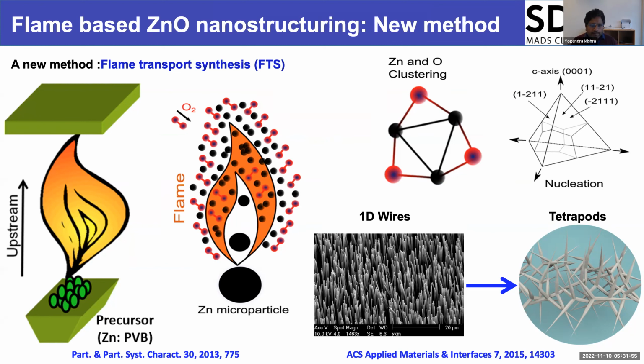nanomaterials, whatever. So in the same approach, I developed a recipe where we take zinc microparticles and polyvinyl butyral as precursor materials. We fill them into a ceramic crucible, and then we put it at high temperature into the oven. Due to the high temperature in the oven, this polymer burns. It generates a flame which carries these particles away into the flame. And due to the high flame temperature, these particles are converted into atomic vapor, which is zinc atomic vapor, and oxygen combines. And then we have growth of zinc oxide micro and nanostructures from the vapor phase. So this is a solid-vapor-solid process.